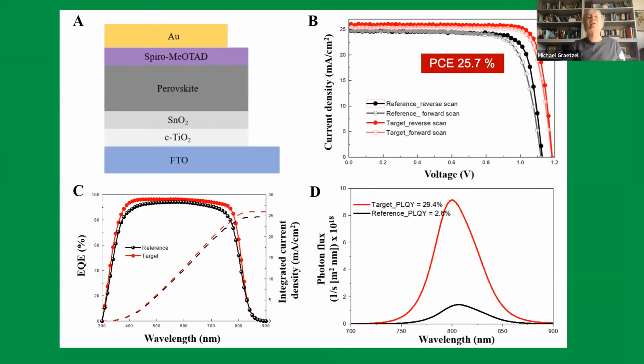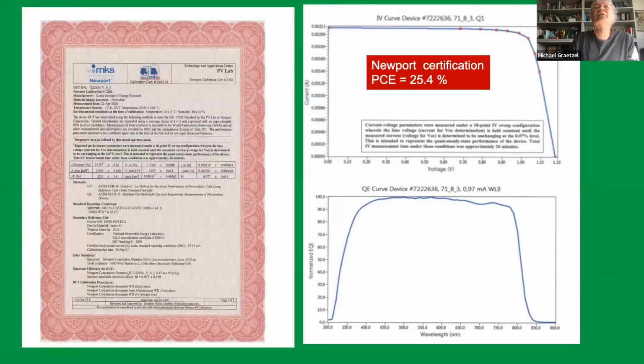And finally, some of the efficiencies we have obtained. And for example, the message here is, between the perovskite and the spiro-OMeTAD, we have a passivator. It's octyl ammonium iodide. If you don't use that passivator, you see the photoluminescence goes down by a factor of 10, and you get much poorer performance. And so to get to those high values, you need to work on the contacts also, not only on the perovskite itself. And so, yeah, these are certified values.